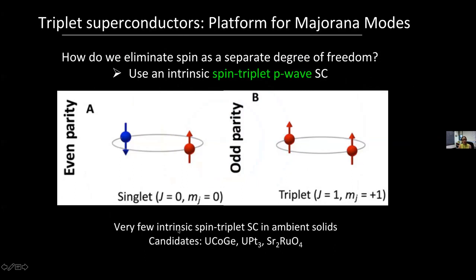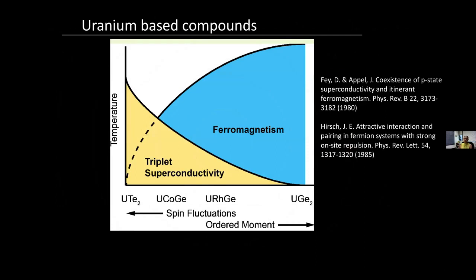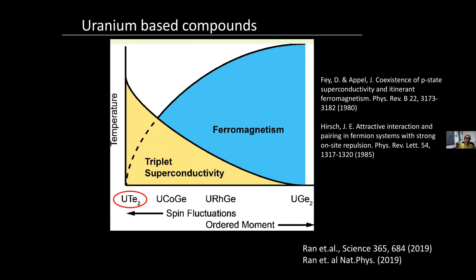The problem is that there are very few intrinsic spin triplet superconductors. We have some candidates — strontium ruthenate may need to come off this list because there's mounting evidence it might be a singlet superconductor, though it may break time reversal symmetry. One common theme among candidates is that many are uranium compounds. Studies from the 1980s tell you that if you want to look for a triplet superconductor, you want to look in the vicinity of ferromagnetism. Uranium ditelluride doesn't have long-range ferromagnetic order, but it must have ferromagnetic fluctuations.